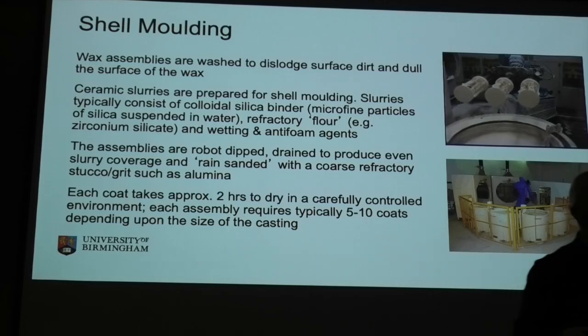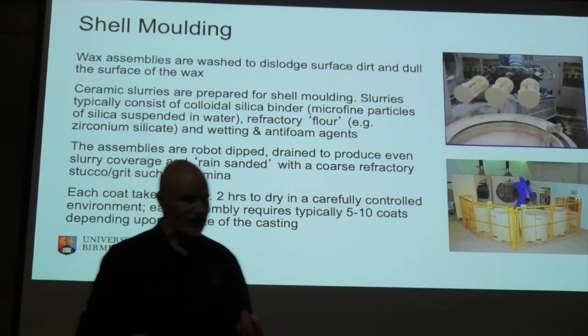The primary coat, the first one, the one the metal sees, best quality. Thickest slurry, finest sand, that's the one that gives you the surface finish. After that, slightly more runny slurry, thicker sand, we're just trying to build up bulk and strength. But then we're going to want to get the wax out.